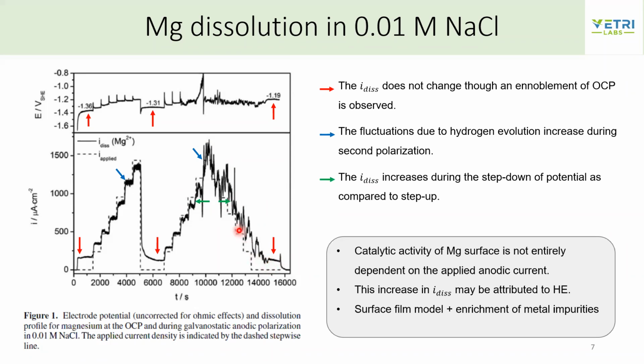However, after the end of the polarization, they were able to see that the dissolution current comes back, falls back to the same value. So what's interesting here is that though the dissolution current falls back to the same value, they found an ennoblement in the OCP after every polarization.